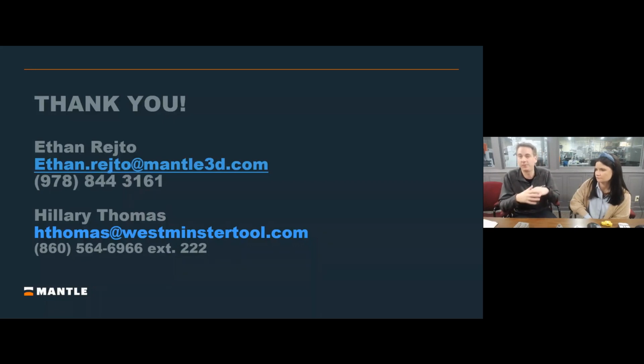Our software is going to fully account for that shrinkage for you. All you have to do is input your end use part, this is what I want to get out of the furnace. We're going to automatically scale that part for you, and that's what's going to be printed. The ability to have such low shrink comes from our paste material. It's highly loaded, a very optimized material, which allows us to get a very tight green body and very minimal shrink, which is critical for our process and for creating precision parts. When you're shrinking 18, 19%, it's much more difficult to control those tolerances.